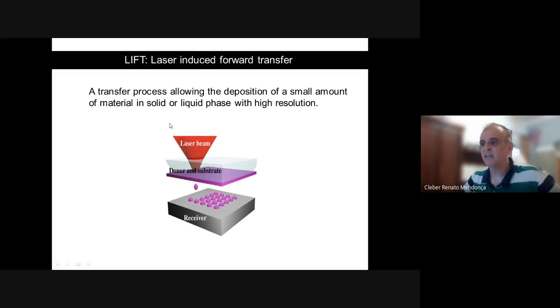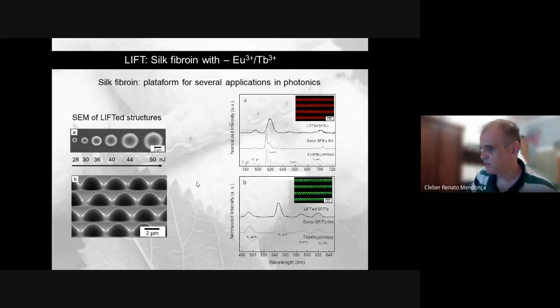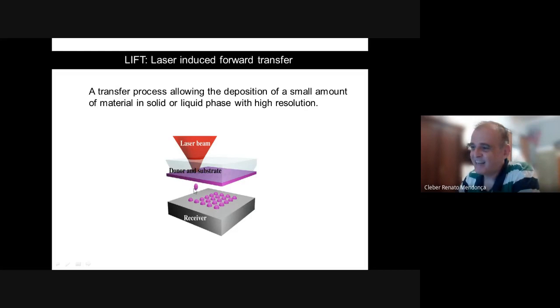Another technique that we use to fabricate micro and nano devices is laser-induced forward transfer. So here is something a little bit different. I have a substrate, let's say a glass substrate, and then I have a donor material. I focus the laser beam in the donor material, and then I explode or melt this material in such a way that I can transfer material from the donor substrate to the receiver substrate by using femtosecond lasers in a very controllable fashion.